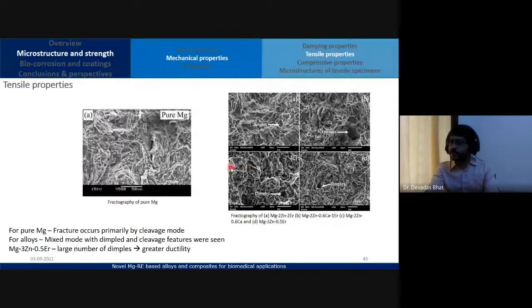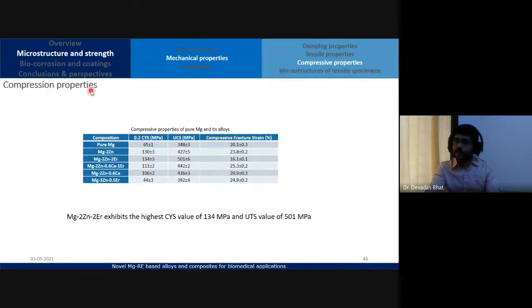Small examples of fractography here: for pure magnesium, it fractures by cleavage mode, and for the alloys, you can see some dimples forming. Compression properties also improved for our alloys. You can see that the ultimate compressive strength is as high as 501 megapascal.